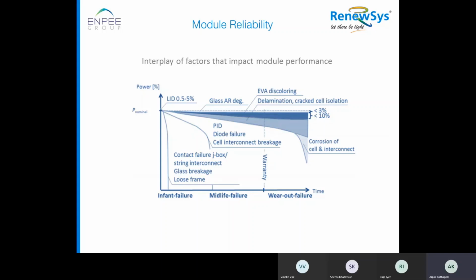Infant failures, whereas at the midlife failures is ARC glass AR coating degradation, PID failures, diode failures, cell interconnecting breakage. Whereas they saw at the end of the warranty, slowly the EVA discolorization will start, delamination, cracking, cell isolation will start, and corrosion and cell interconnection for a period of time. Broadly, these are the major defects what NREL studied in their reliability studies. We'll see how RenewSys is taking care of all these defects, how it is mitigating all this risk while manufacturing the modules.